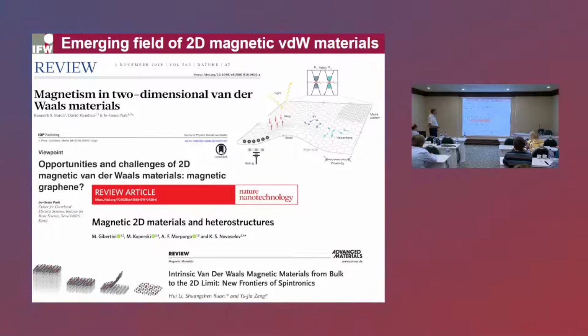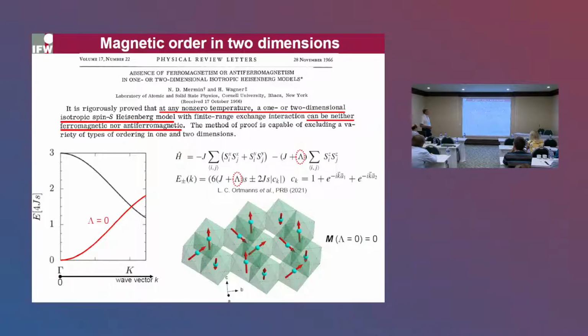But actually, the most important property of this single layer should be that it should retain a magnetic order. And this is the greatest problem, because it confronts the very famous Mermin-Wagner theorem, rigorously proved in the middle of the last century, that at any non-zero temperature, a one- or two-dimensional isotropic Heisenberg spin model can be neither ferromagnetic nor antiferromagnetic. That means as soon as you increase the temperature above absolute zero, low energy spin waves will be excited in the system, which need an infinitesimally small energy to get excited, and the long range order will be destroyed in the two-dimensional limit.